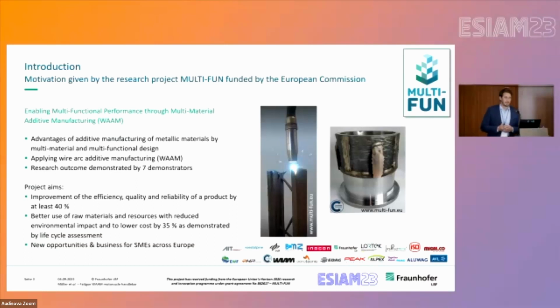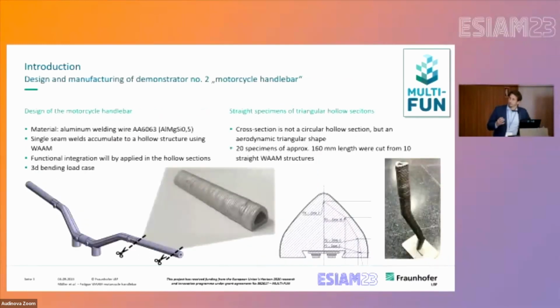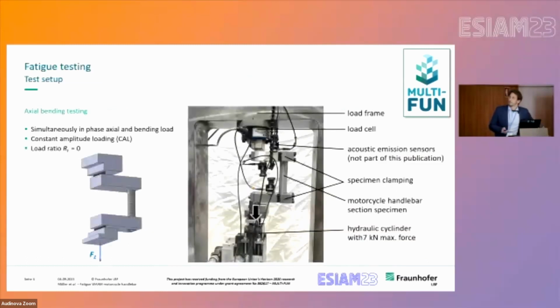In the case of the motorcycle handlebar, the idea is also integrating functionalities, copper wires, for example, finally for the later application. In this case, we focus on the base structure, which is not just a circular one as it might appear here, but finally an aerodynamically designed cross section made of the aluminum welding wire AA6063, produced using the WAAM process. We see such a part structure of the motorcycle handlebar here to the right, which was the basis for the cutting of such specimens, so straight specimens, hollow sections, for the fatigue assessment later on. And the load case is not just an axial one, but a bending load case.